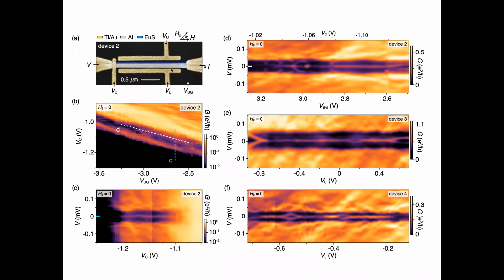So one of the things that I would be expecting if what I see here is a zero bias anomaly that somehow is entering into the topological phase and then going out, because, for example, in your figure D, at the beginning, you have no zero state, then it appears. So I would expect that the whole bands would go to zero, closing the gap, and then reopening, whereas what I see here is what we typically observe when we have these, let's call it quasi-Majoranas or pseudo-Majoranas or non-topological Majoranas, where you have a lone detached state going towards zero. This could be something signaling that this might not be Majoranas. You mean because you don't see gap closures associated with splittings? Exactly.